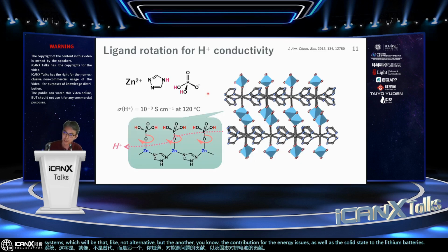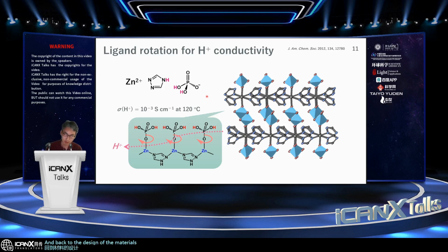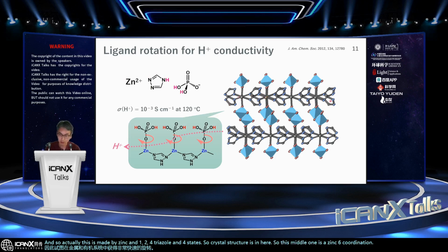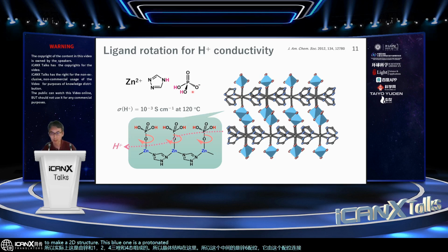Back to the design of the materials, we thought that solids having some rotating motion would be very important. So we tried to get very fast rotation in metal-organic systems, as shown here. This is made of zinc, 1,2,4-triazole and phosphates, and the crystal structure is here. The middle one is a six-coordinate zinc, linked by 1,2,4-triazole to make a 2D structure. This blue one is a protonated phosphate, okay?